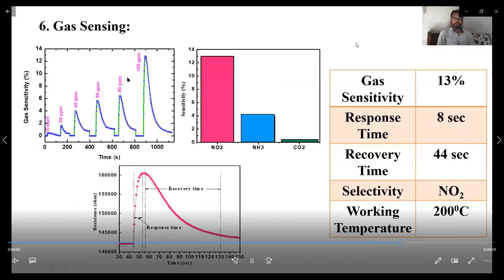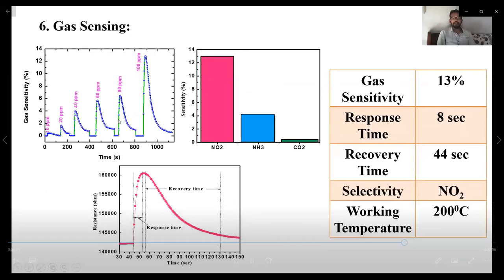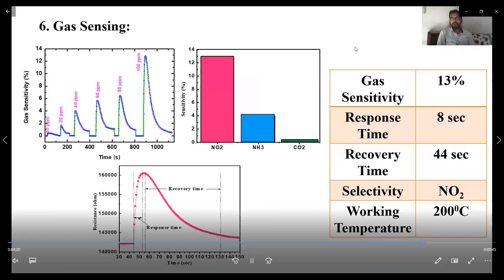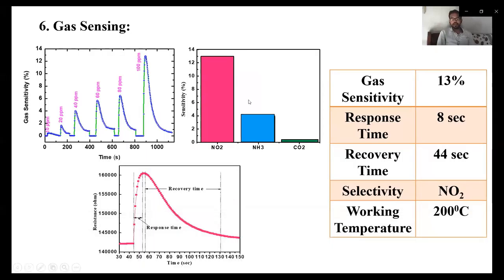The last one is gas sensing. This is a gas sensitivity versus time graph. This shows the sensitivity of the prepared material, and the sensitivity is 13% for 100 ppm NO2 gas. This is a selectivity graph. This shows that the prepared material has the highest selectivity towards NO2.